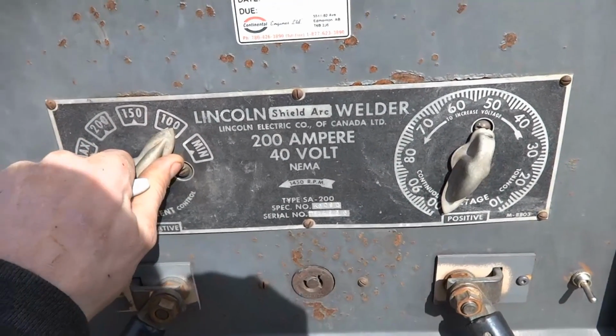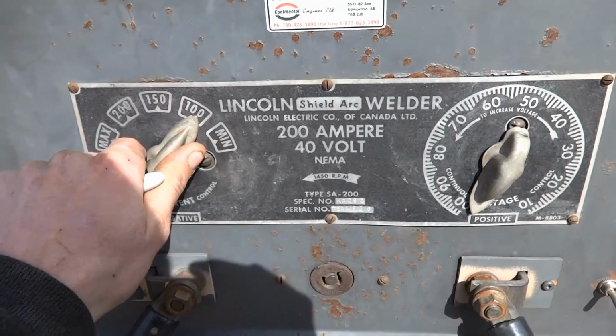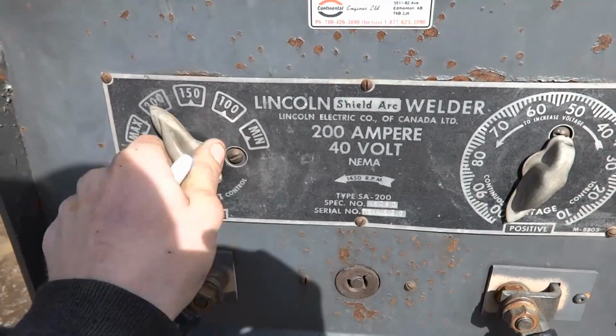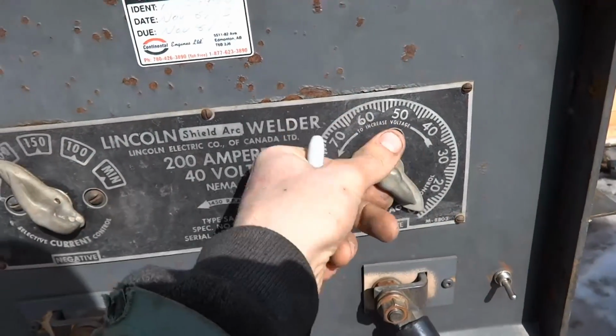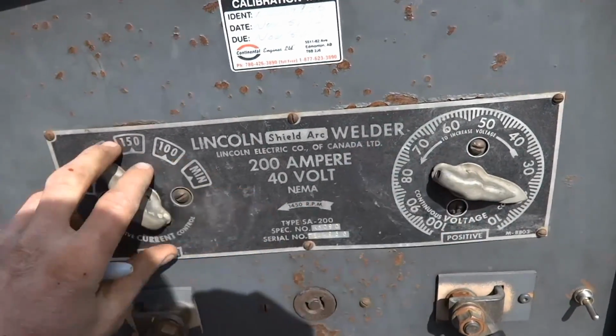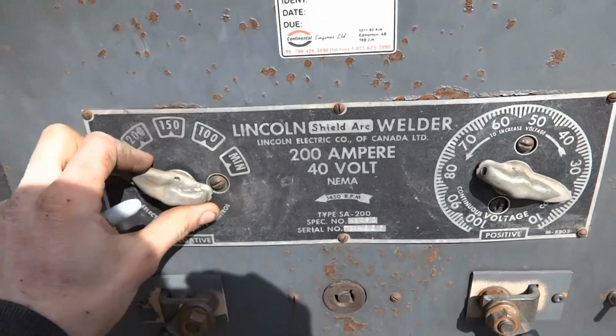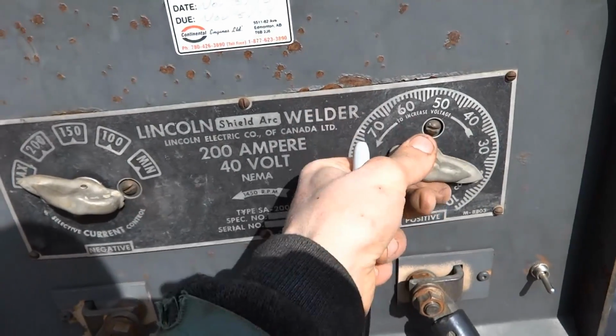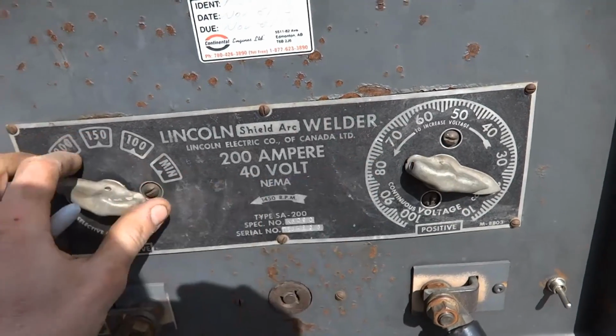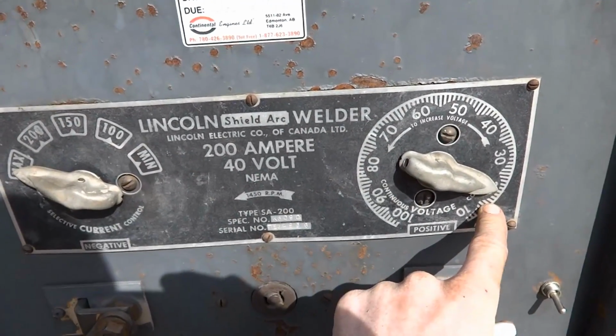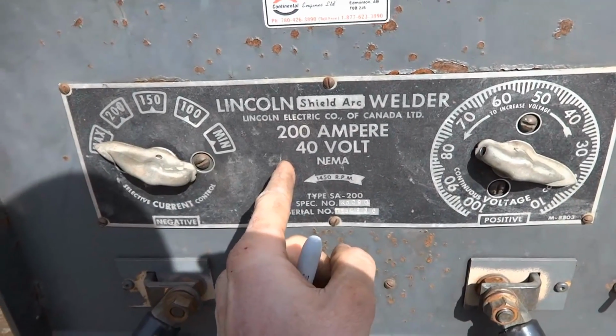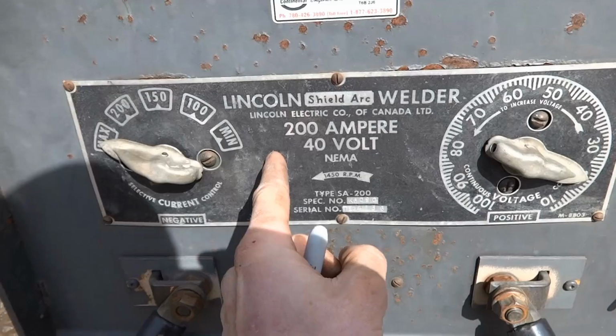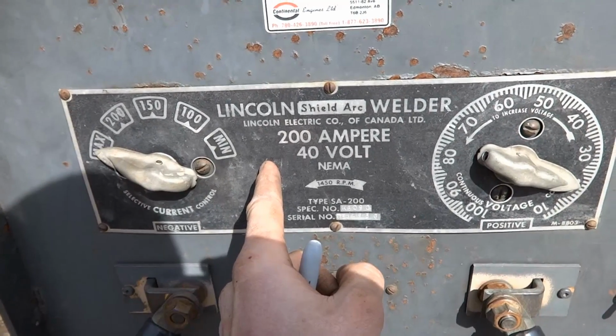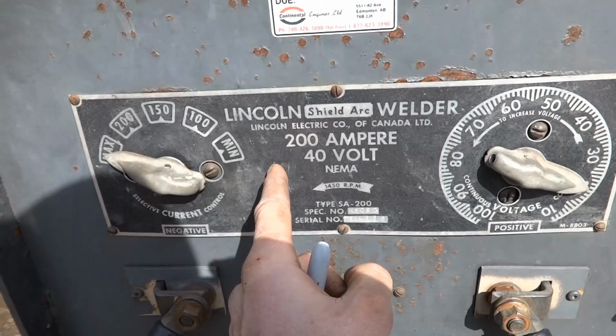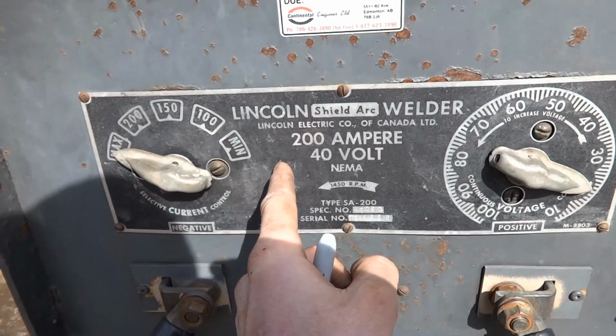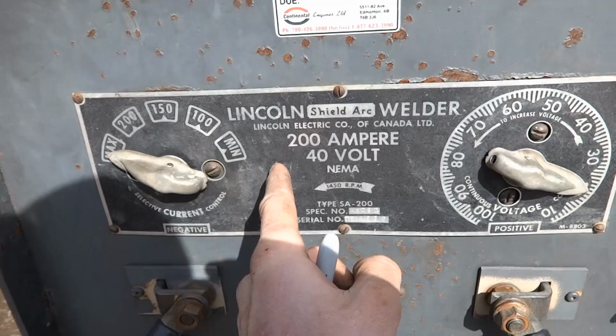If you're stacking metal, say vertical up, 7018, heavy wall pipe, you'll be in 4th gear, 10 and 20 volts. That's with a 1/8 electrode, 5/32 electrode, 5th gear, 10 and 20 volts. With the reduction of voltage, when you're at the left hand side, you can hold a tight arc into the side of the pipe there. Amperage increases, burn off rate increases, voltage drops off. The puddle solidifies because of lack of voltage, and the burn off rate increases. It deposits a lot of metal in a very short amount of time.